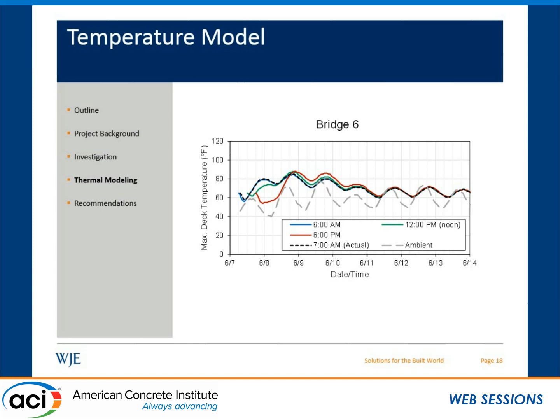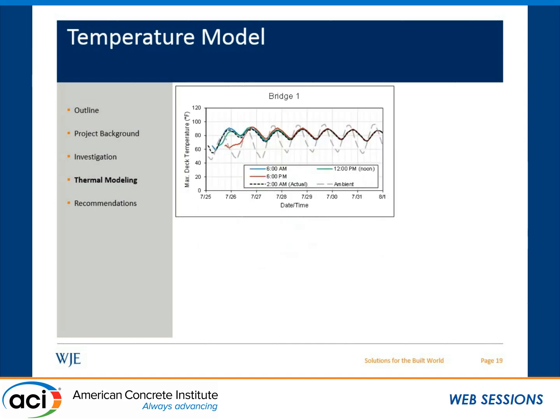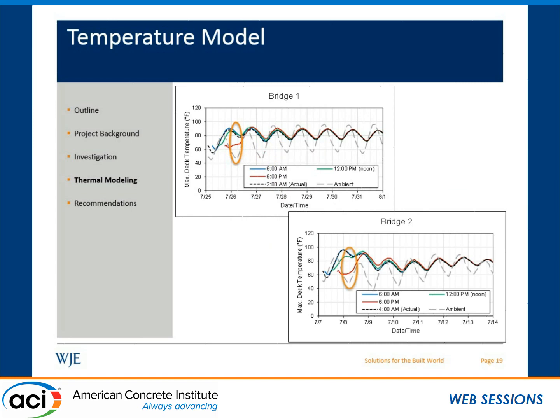And what you can see is that about 24 hours in, we have a very large difference between the temperature of our concrete and the ambient temperature. It's about a 35-degree difference. And we saw these same effects for the other bridges that we modeled. So this is Bridge 1, and you see a very large difference about 24 hours in. And we saw the same thing for Bridge 2, about 24 hours in.